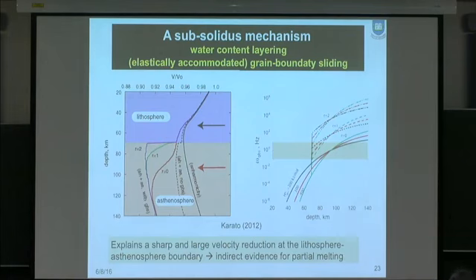In terms of subsolidus mechanism, you could explain the lithosphere-asthenosphere boundary and the relatively large velocity drop by invoking a relatively large jump in hydrogen content caused by partial melting. So in a way, a velocity drop like this is an indirect consequence of partial melting, not a direct one. Then you can come up with a model to explain the lithosphere-asthenosphere velocity profile.